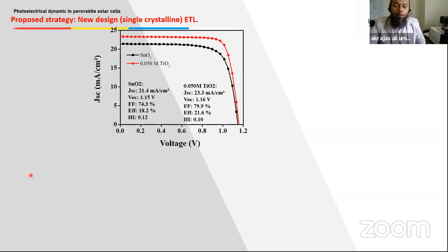This is a typical example of the performance we have recently. That is a nanograss based device. We get efficiency as high as 21.6%, which is among the highest reported using TiO2. We use a triple cation perovskite system, and the fill factor is quite high, around 80%. We also report VOC; the theoretical limit is up to 1.18 volt, but for this optimized device we have 1.16, which is also one of the highest VOC reported so far.